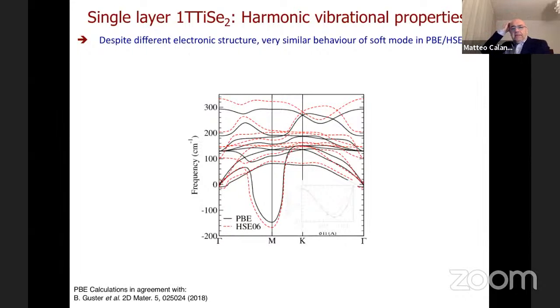What we did at the beginning is to calculate the vibrational properties of the IT phase at zero temperature. Of course, the IT phase at zero temperature is unstable because the system wants to distort. If you calculate the phonon frequencies, you find an instability, namely negative phonons. Negative phonons are, for me, imaginary eigenvalues of the dynamical matrix. I plot an imaginary eigenvalue as negative, and the instability occurs at the M point, consistent with a 2x2 reconstruction.